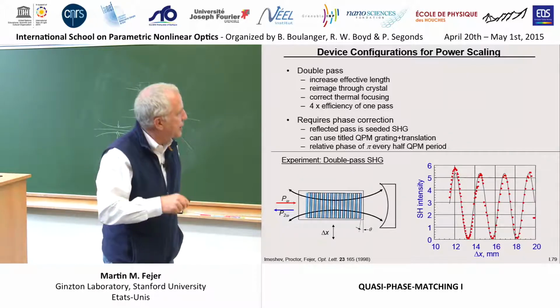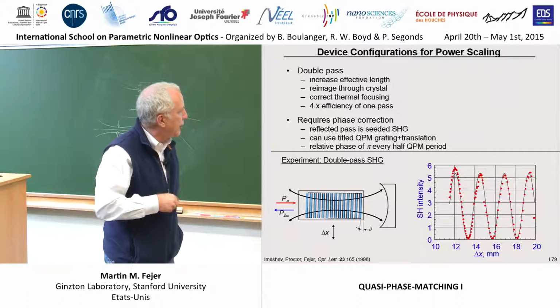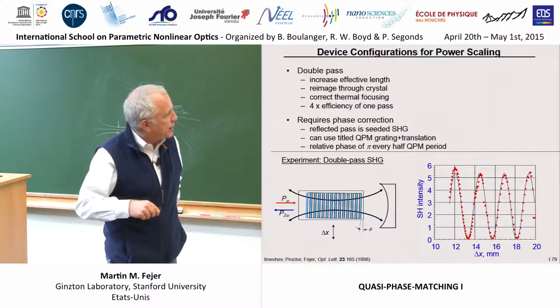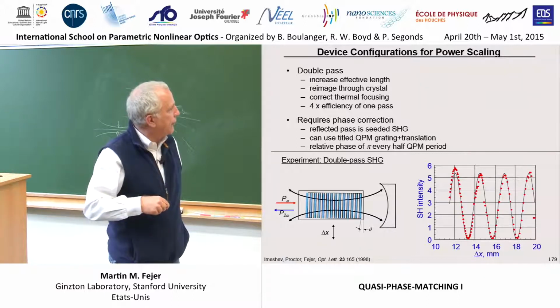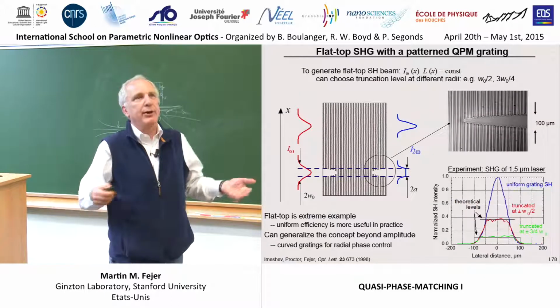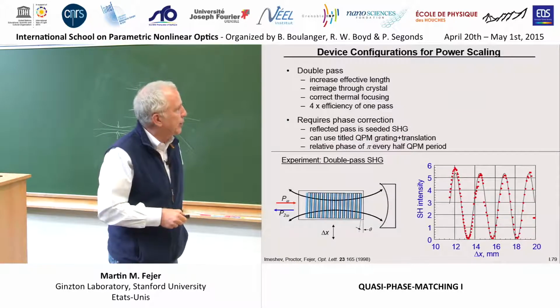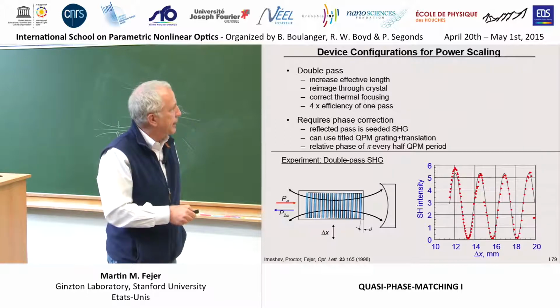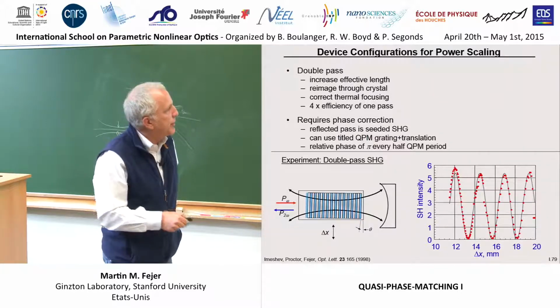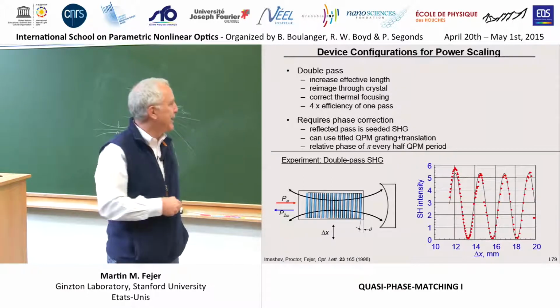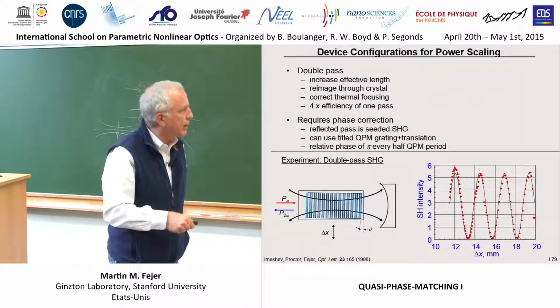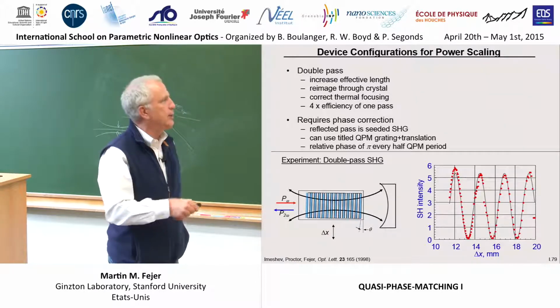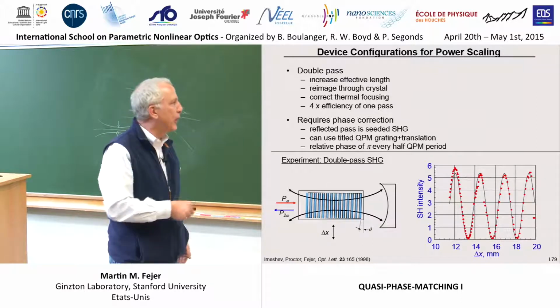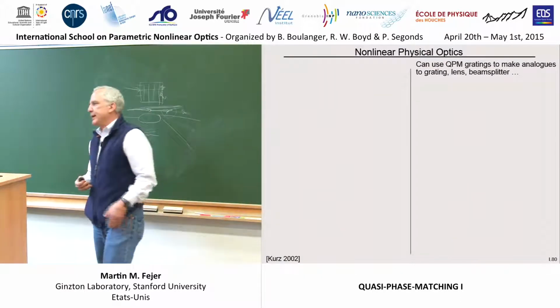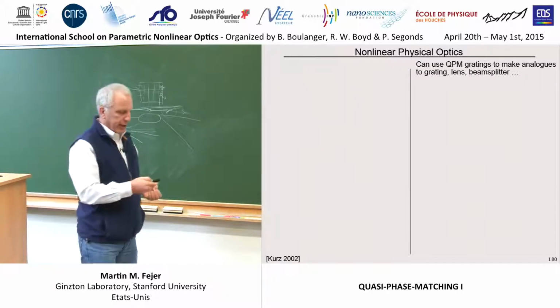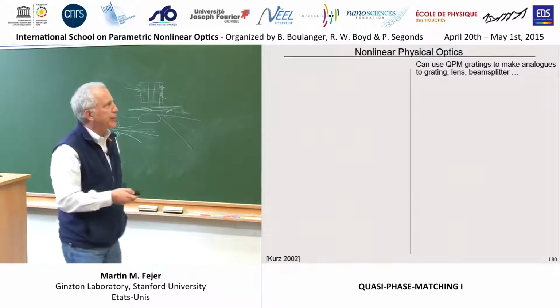Here we're translating the crystal some distance. Here we're monitoring the second harmonic coming back after a second pass. And you see that if you do it exactly wrong, the forward pass is exactly canceled by the second pass and you get nothing out. If you do it exactly right, and I guess the calibration here is not very useful, but this is 4 times what you had in the forward pass in a single pass device. So you go periodically as you translate this thing from in phase to out of phase to back in phase. And so it's an easy and, again, lossless way to make this kind of adjustment available to you in a QPM structure that otherwise would require additional stuff in your apparatus.